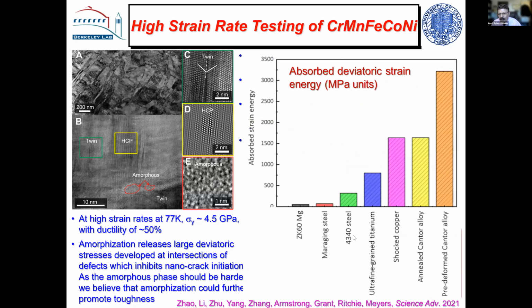So if we look at the toughness of these alloys, you don't measure a conventional toughness, it's absorbed strain energy, basically. These very highly strained alloys have the highest toughness compared to a whole bunch of other materials you might test. It's a bunch of steels, maraging steels, titanium, copper, and the like. Again, it's this multiple generation of deformation mechanisms, and even now amorphous material, which sustains the strain hardening, which is the key.